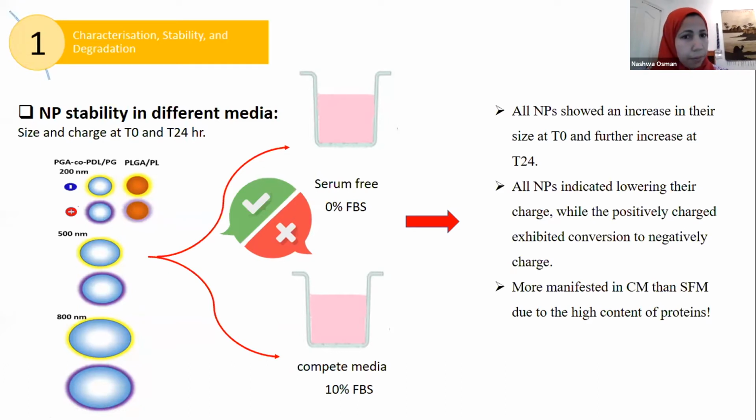So I've done this for my experiment. I did the characterization at T0, which is immediately after dispersion, and after 24 hours. What I noticed is we get an immediate size increase once we add them to any type of culture media, because the nanoparticle is going to interact with components inside the culture media and definitely absorb a lot of these components onto their surface. Then it will increase their size.